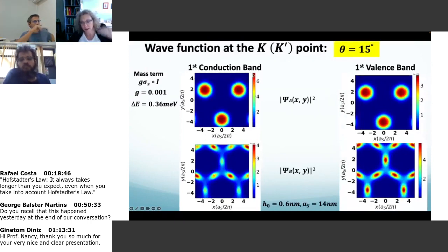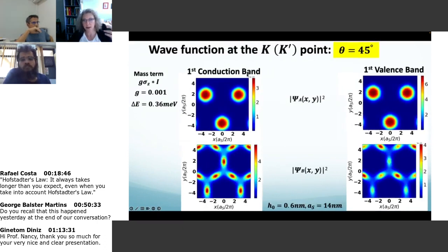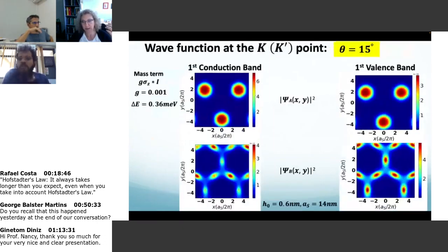Now, if I change the chemical potential and I go to the valence band, this state has negligible contribution. So in the valence band, I will see these guys. So these will be the holes, and the holes will have Chern number -1. So if I change the chemical potential, I will go from a trivial insulator to a topological insulator. That's basically what happens for this orientation.